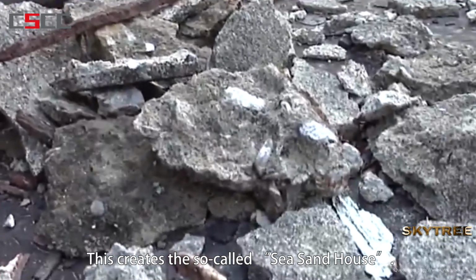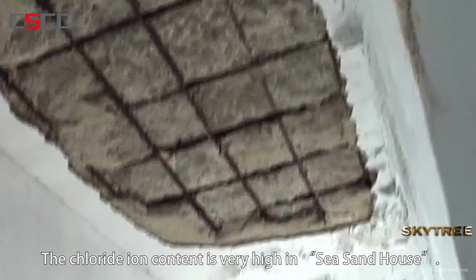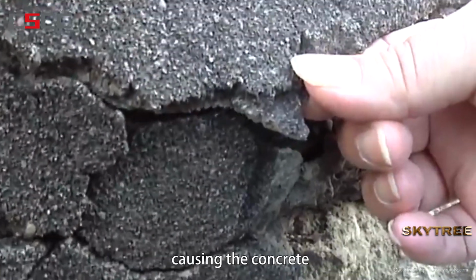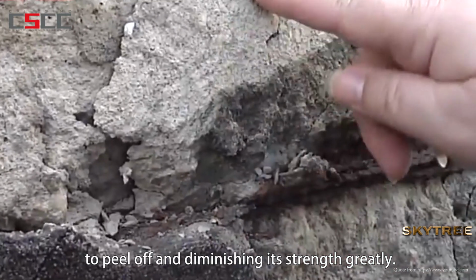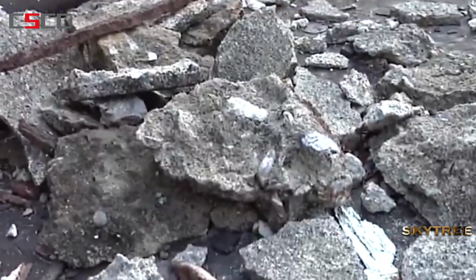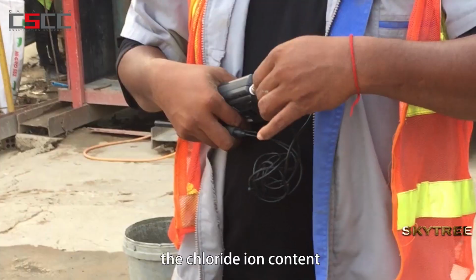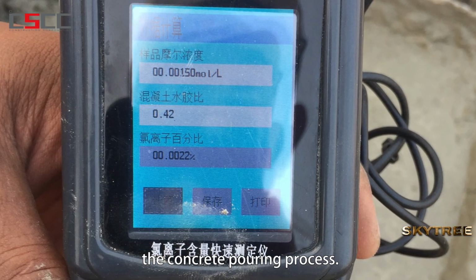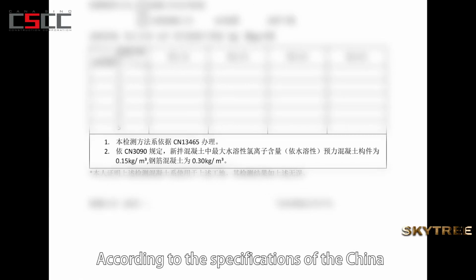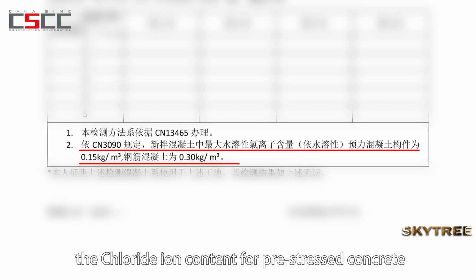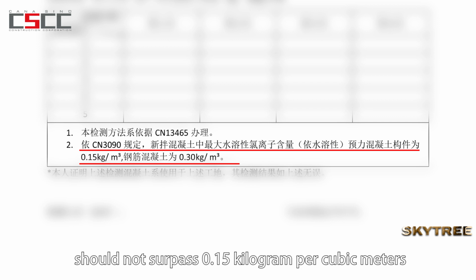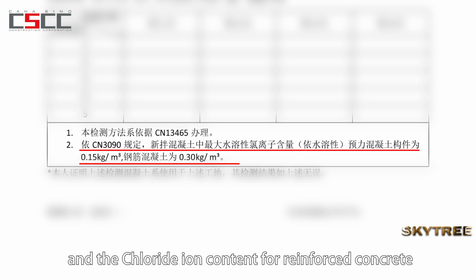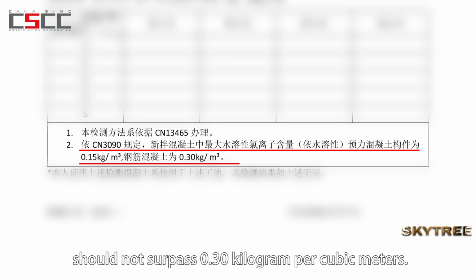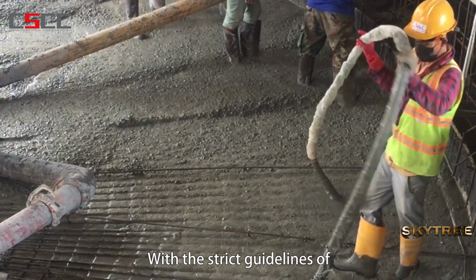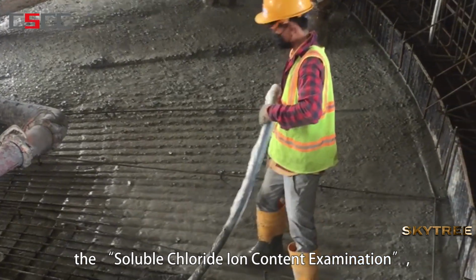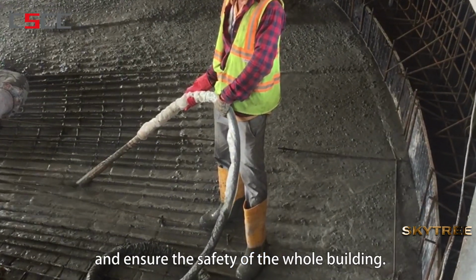This creates the so-called sea sand house. The chloride ion content is very high in sea sand house. It gradually corrodes the rebar of the building, causing the concrete to peel off and diminishing its strength greatly. It even creates hidden dangers in the architectural structure. Thus, to prevent the sea sand from entering the building material, the chloride ion content must be examined closely during the concrete pouring process. According to the specifications of the China National Standard CN is 3090, the chloride ion content for pre-stressed concrete should not surpass 0.15 kg per cubic meters, and the chloride ion content for reinforced concrete should not surpass 0.30 kg per cubic meters. With the strict guidelines of the soluble chloride ion content examination, we can prevent sea sand from penetrating the structure and ensure the safety of the whole building.